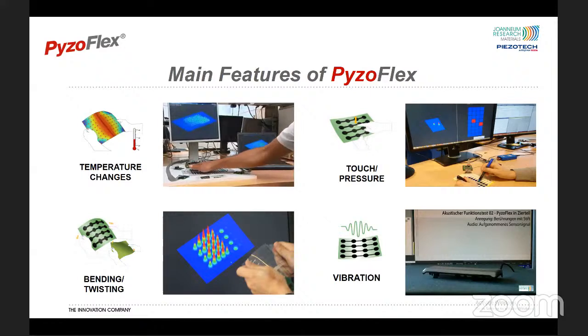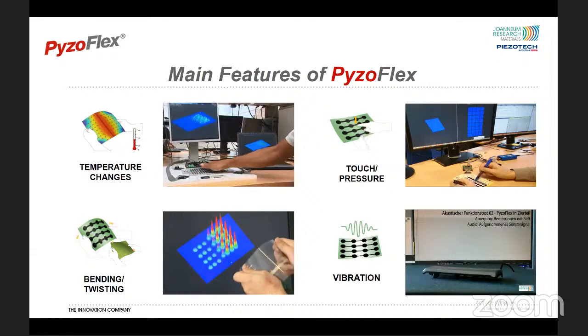Pyroelectricity, which is the sensitivity against temperature variations, is exploited in this example for proximity sensing. Then we have piezoelectricity, the sensitivity with respect to pressure and touch, whereby in this video a non-conductive touch interaction is demonstrated. We have then also mechanical flexibility that can be used, for instance, for the definition of novel bending gestures in a 3D input sensor, as it is shown here. And finally, also structure-borne sound and vibrations can be registered, which in this case the PyzoFlex foil is adhered to the backside of a metal trim part and transforms it into a microphone.